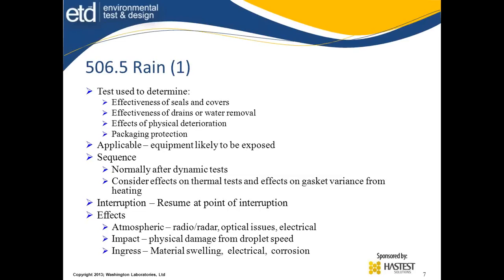When I'm looking at hard surfaces like metals and the like, you don't really see that by itself as being the effect, but the deterioration of paints and etc. causing the readability of labels, that's a problem. And if it does ingress, material swelling, the electrical portion of this, and the associated corrosion, because the moisture that does ingress results in a steam bath going on inside from the heating of the material during operations, so you end up with corrosive effects associated with it.